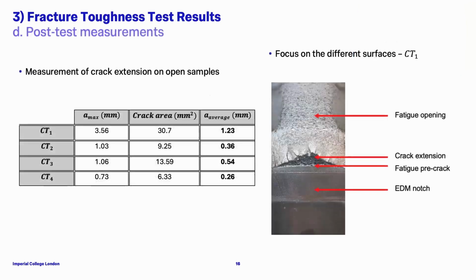And then I wanted to see if my values were in good agreement with the physical measurements. So when I opened my samples entirely, I measured the final crack extension. And so here are the final crack extensions I measured physically. They are much lower than the ones predicted by the four JR curves I've just shown you. They were predicting about 6 millimeters, and we are sometimes not even at 1 millimeter.